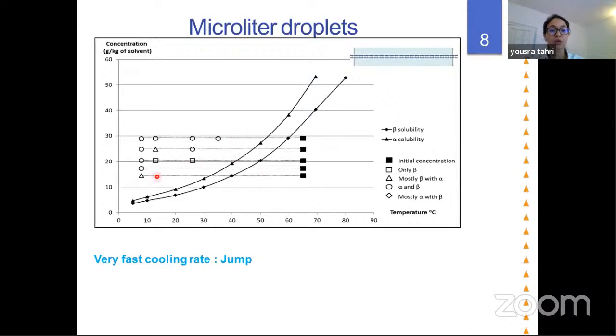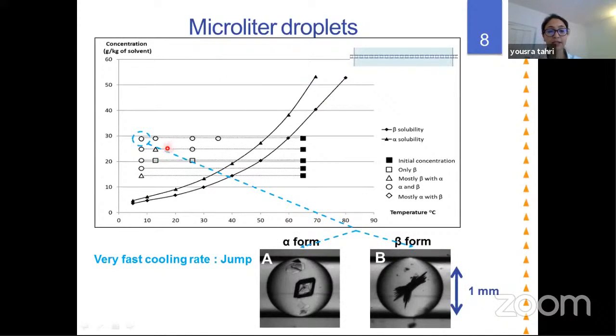So in general, what we observed is that we mainly had the stable phase beta, with some droplets where we could observe the metastable phase alpha. For example, here for this experiment, you can see a droplet with one crystal here, which is the alpha phase, and another droplet with the beta phase. In some droplets, of course, we could observe both polymorphs, and even here you can see that there are some crystals of beta next to the crystals of alpha.